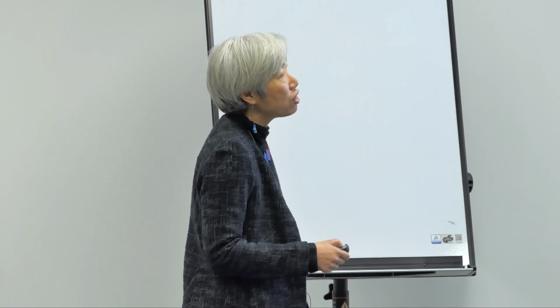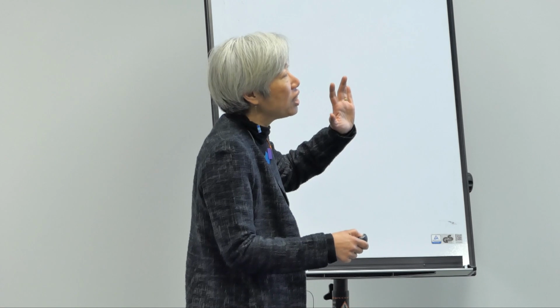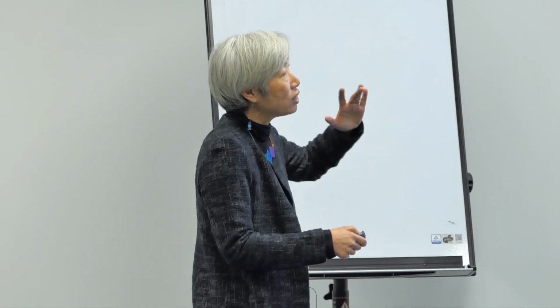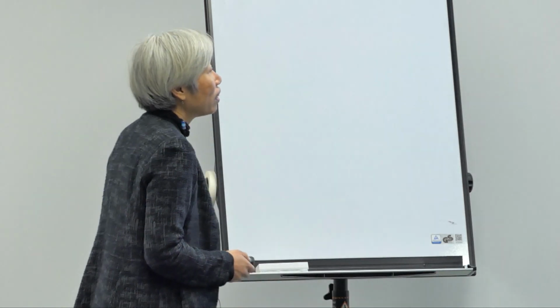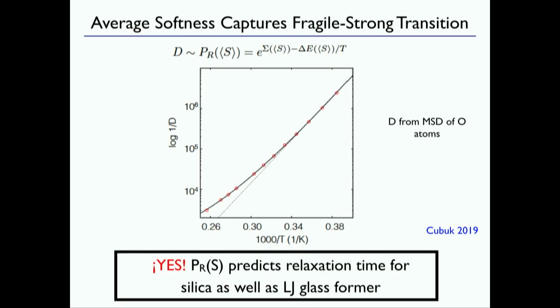So we can predict the relaxation time in this system. And silica actually has what's called a fragile to strong transition, so that at really high temperatures it's Arrhenius, and then it becomes fragile at intermediate temperatures, and then strong or super Arrhenius, and Arrhenius at sufficiently low temperatures, and we get all that. That all comes out. So yes, really different system, and it still works. So we can cover the whole spectrum from strong glass formers to fragile glass. It seems to work. All right, so we're really happy with that.